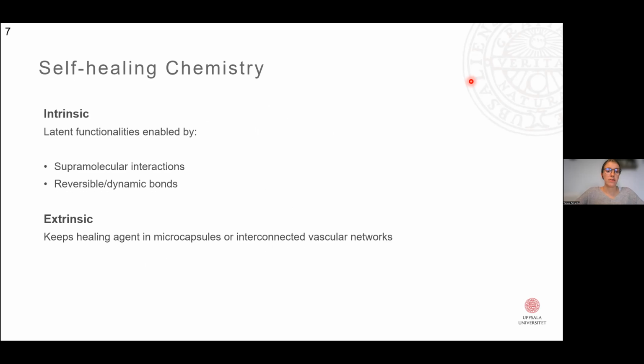If we just look again briefly at the self-healing chemistries that we heard about, we often divide them into intrinsic and extrinsic self-healing, as Anja also mentioned before. And these latent functionalities enabled by supramolecular interactions like hydrogen bonds or dynamic covalent bonds are coupled to this intrinsic self-healing. And this is where I will be putting my focus today, because these ones are very good for binder systems, since they have multiple healing cycles and have this reversibility that we can utilize. This extrinsic self-healing, for example, is where you can use microcapsules or vascular networks and put the healing agent inside and more locally spread the healing agent in the battery or where you want it, and use the self-healing through that. But my focus will be on this intrinsic.